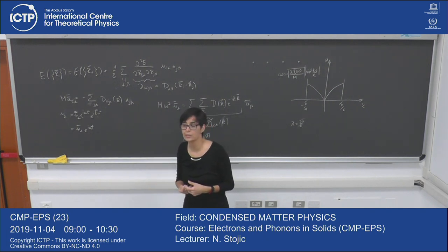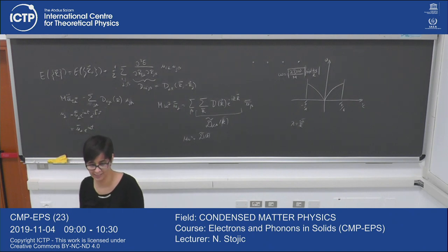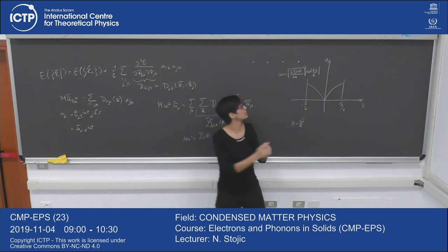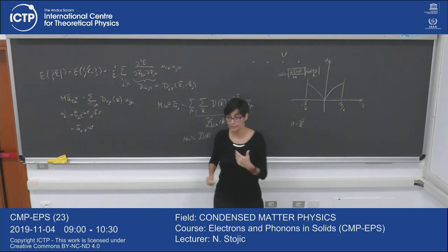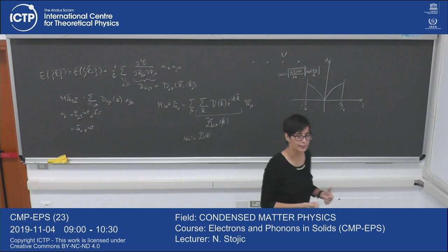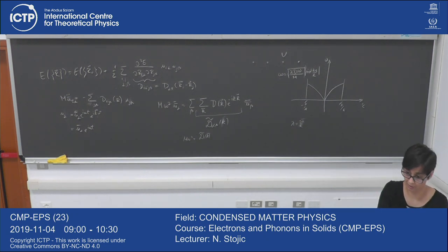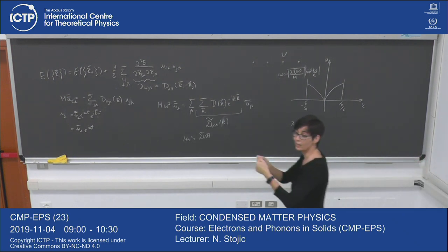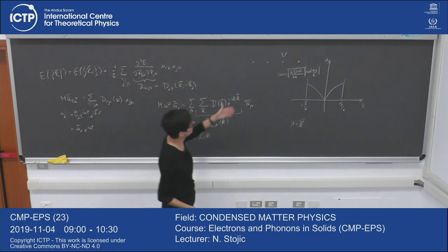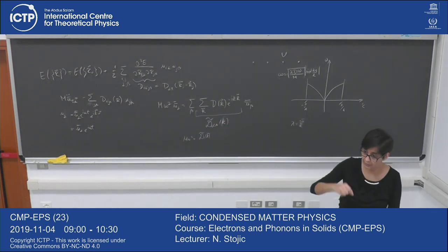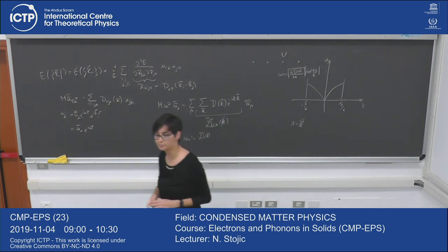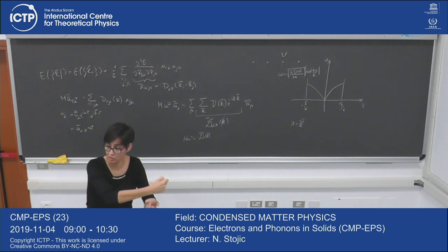There is no this kind of crystal symmetry in air. There is no symmetry, of course, and there is no restoring force. Yeah. In the crystal, when you move an atom from its equilibrium position, there is a restoring force which pushes it down. This square. There is no such thing in air. So actually in the air, the sound waves can propagate only as an accumulation of particles, like a change of pressure. It can be in only one way. Today we will make a difference between two different types of motion. In crystal, in more than 1D, it can move perpendicular to the propagation direction, and move along the direction in a 3D crystal. Well, in air, it can go only in the direction of propagation.